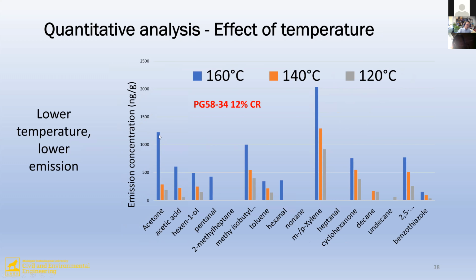Those kind of emissions. But if you reduce the temperature, now you can see maybe this one about 300 or 350, or 200 something. But for all the elements, like xylene, for example, this one here was like this high, like 2000 or something. You can easily reduce that one to less than 1000 when you reduce temperatures.